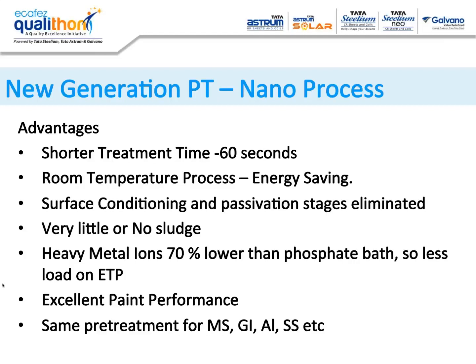So this coating is literally very small, 50 nanometers to 200 nanometers is the range. It will of course vary a little from company to company. There are only 3 or 4 companies who have an established marketable product at present.